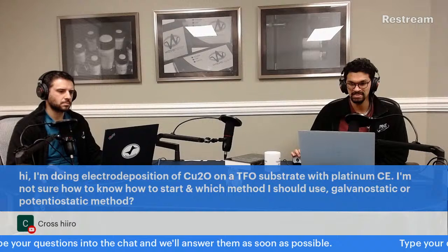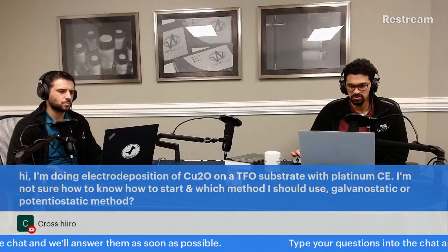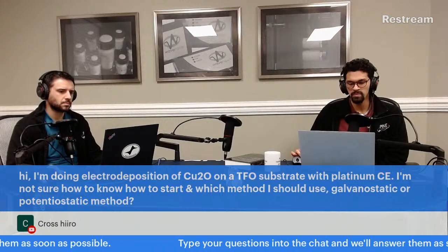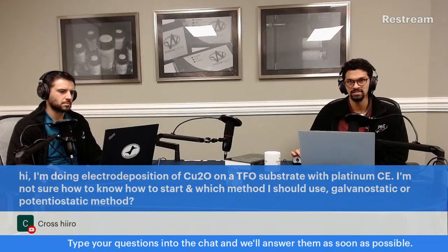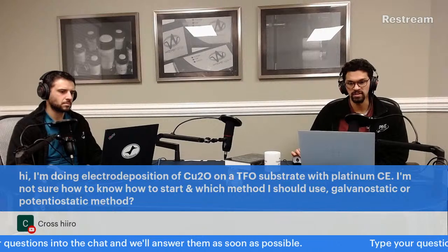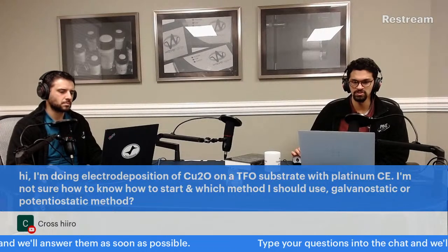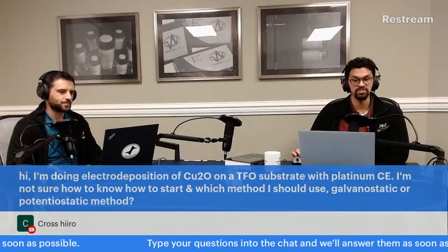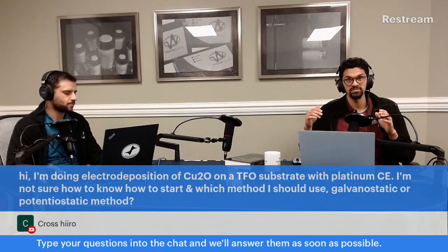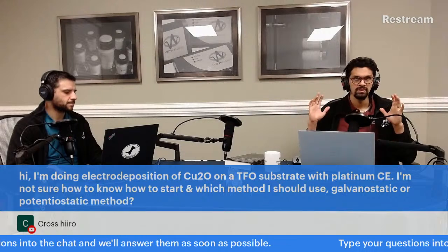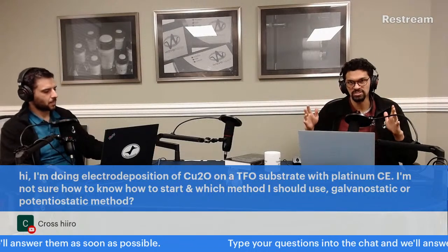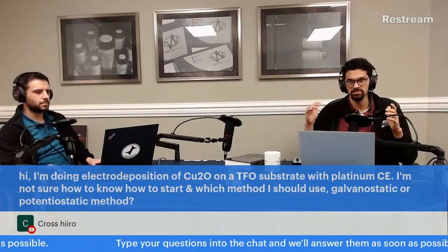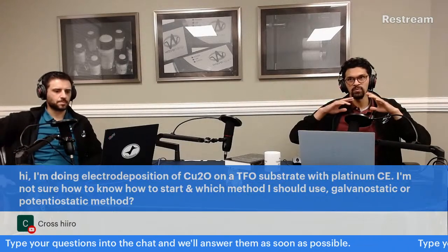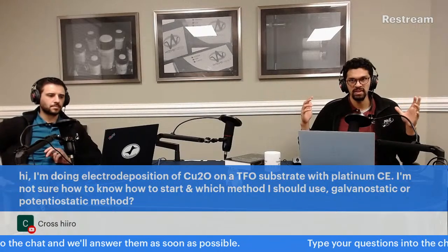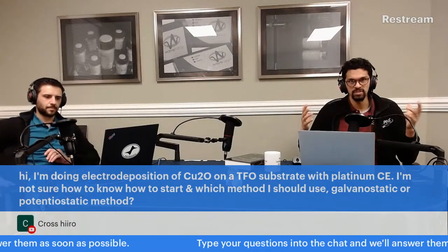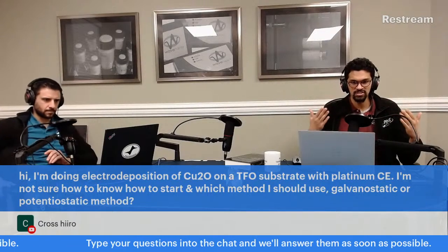Specifically, I would do something like cyclic voltammetry, because currently you don't know at what potential copper oxide deposits on the FTO substrate. You may even want to just do cyclic voltammetry of FTO in your electrolyte itself, because you don't know what your electrolyte's going to do. By doing experiments potentiostatically, such as cyclic voltammetry, you'll get an idea of all the things in your system that could be affecting the electrodeposition process. So that's my recommendation of where to start.